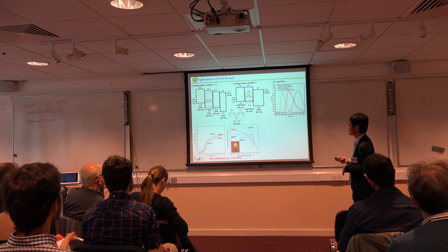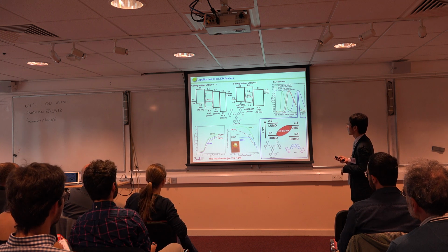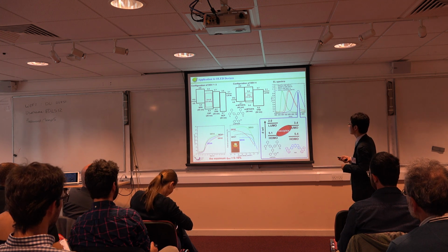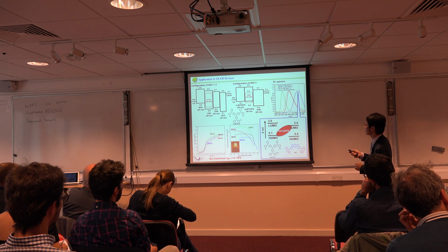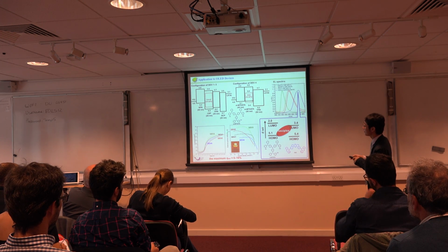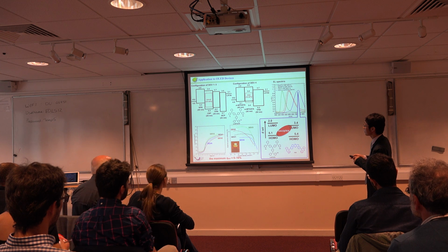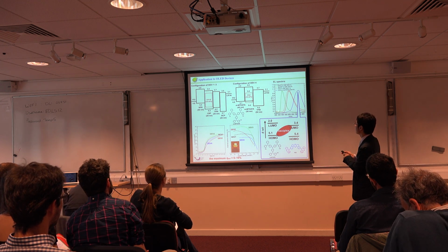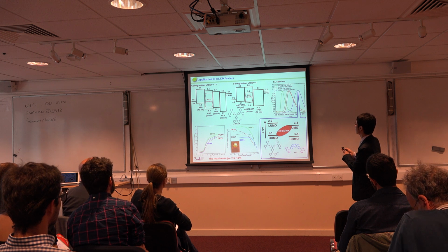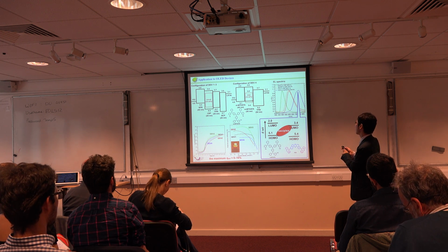So using these materials, we fabricated devices, and as you can see, the devices showed good EQE up to 60%, with emission from green to orange to red.